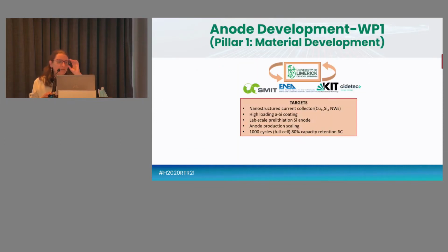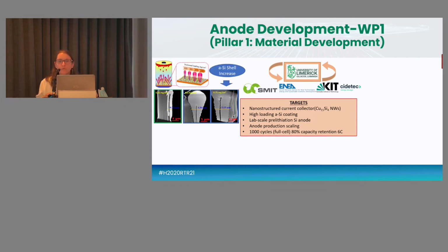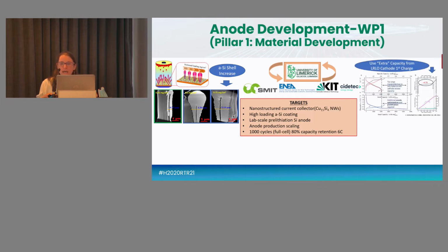For the anode development within work package 1, the University of Limerick is leading this work package. Basically, we are developing a nanostructured current collector that is a copper silicide core surrounded by a high loading amorphous silicon coating. At the moment we are at the stage of 1 mg per square centimeter of amorphous silicon that we are able to deposit.